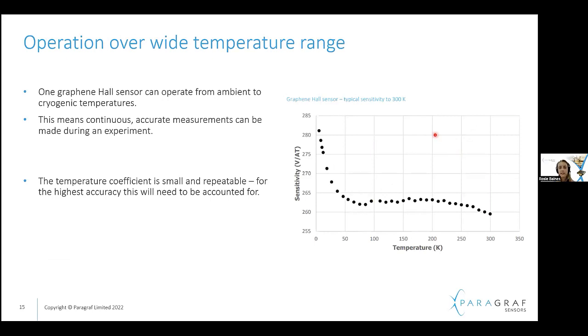This sensor does operate over a wide temperature range. So we can see here going all the way from extremely low temperatures to ambient temperatures. This means that with one sensor, you could have a continuous and accurate measurement through the entire range. And the temperature coefficient is also quite easy to calibrate for because it's small and repeatable. So quite easy to have a handle on the behavior there.